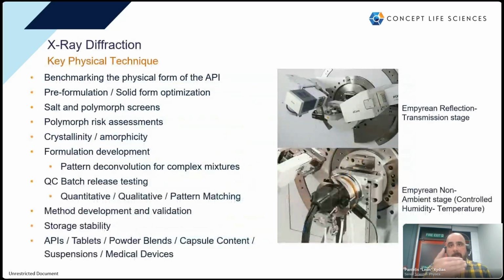And for those reasons, just because it is very characteristic of the phase within the powder sample, X-ray diffraction is practically the key physical technique to characterize the structural properties of APIs. It can be employed at all stages of drug development, either in the early stages, benchmarking what your physical form is, or in our case, identifying the different salts, the different polymorphs, optimizing the phase that we're going to be using, as well as identifying how crystalline our material is,